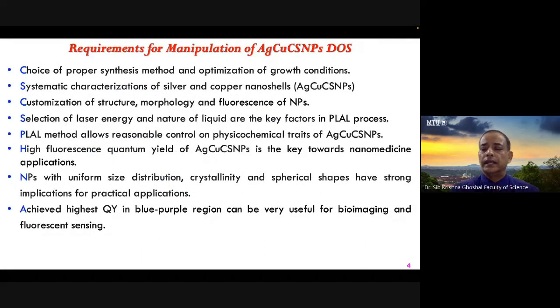So as I pointed out in the beginning, these nanoparticles have to be produced by a very efficient method. The morphology of the nanoparticles must be tailored or customized by varying the parameters of the method. These nanoparticles have to be produced at mass scale, large scale, for commercial application needs. Now look, small industries cannot always afford buying these expensive nanoparticles. They are very expensive. If you look at a few grams from Sigma-Aldrich or from Merck, if you order this kind of nanoparticles with stability of 1 year, with nanoparticle size distribution between 25 to 40 nanometer, 8,000, 10,000, 40,000, 50,000, depending on the nature of the nanoparticle, is the cost in terms of dollars.